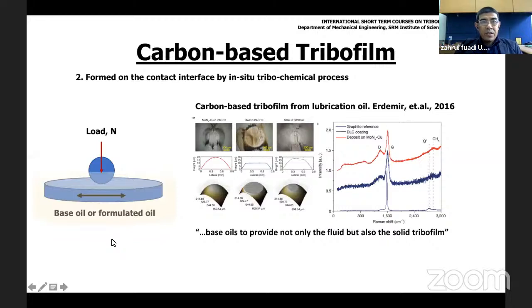The second one is that such a tribofilm can be formed on the contact interface by in situ tribochemical process. This example shows that the contact interface is not coated by any coating, using only base oil or formulated oil with some additive. But here we can see that after some friction, some carbon-based tribofilm has been formed on the contact interface. And this is shown by this graph here, that it has peaks in the D band and G band. So it can be formed on the contact interface by in situ tribochemical process without coating.